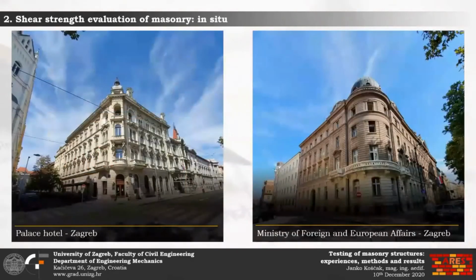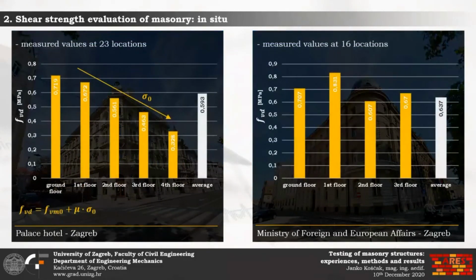Here on this slide, measured values of masonry shear strength for two buildings are shown. On the left, average values for each floor of the Palace Hotel in Zagreb are shown. The values range from about 0.7 on the ground floor to about 0.3 megapascals measured on the highest floor. This is logical as normal compressive stress decreases with the building's height, so the shear strength measured with a simple test also decreases. However, the tests conducted on the building of the Ministry of Foreign and European Affairs, these results are shown on the right, show that this is not always the case, so additional measurements can be of great importance.